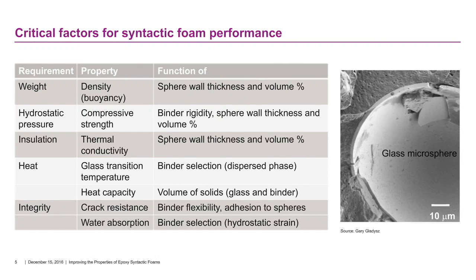The opposite of that would be in the case of overall integrity of the foam to resist cracking. Here you'd actually want the binder to be a little bit more flexible, and perhaps adhere to the spheres if that's necessary. In some cases you do not want sphere adhesion, so you have to strike a balance between those two. Water absorption is going to lead to ingress and slow degradation of the foam itself and just a deterioration of the foam. Binder selection comes into play there.